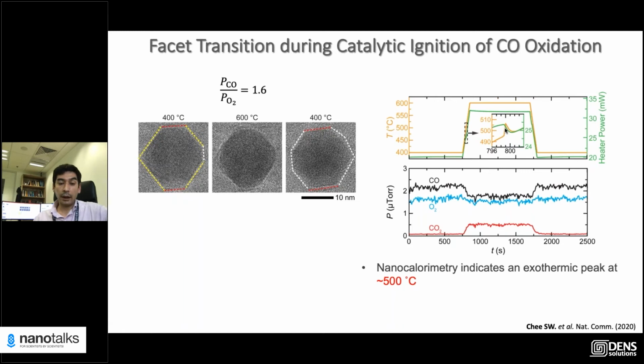It kind of makes sense. So again, I'm going to skip a lot of details, but why do these facets form? When CO binds to the nanoparticle surface, it actually stabilizes the nanoparticles with low index facets. So when the nanoparticle surface is stabilized with low index facets, and you increase the partial pressure, you have to increase your ignition temperature to start the reaction, because now your surface is contaminated or loaded with CO. And if you make the pressure even higher, then the amount of CO on the surface is higher. So with the increased content of CO, your ignition temperature is going up.